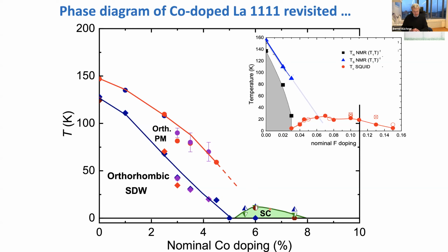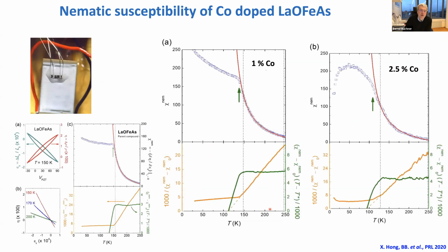So now let's start. We have now single crystals at hand. Let's start to do more experiments. And the first thing what we can do, it's well established, meanwhile, is nematic susceptibility measurements. So what we measure here is the strain derivative of the resistivity. So we have a piezo, we have crystals glued on top of that. We measure the strain, we measure the change of the resistivity, plot resistivity as a function of strain, take the derivative, we get the nematic susceptibility. This shows this divergence close to the structural phase transition.